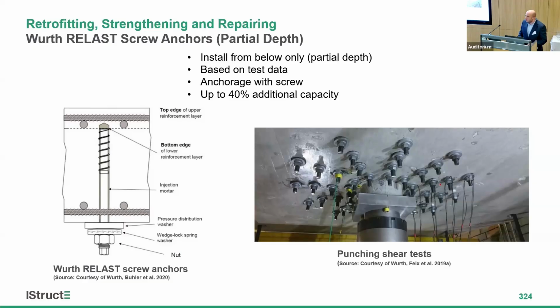The design of these is all based on test data, which has shown up to 40% additional capacity can be achieved. But it's reliant on this test data, and it obviously doesn't have as good performance as if you can go all the way up through the slab. However, if you only need a nominal amount of additional capacity, up to 40%, this can be a good option.